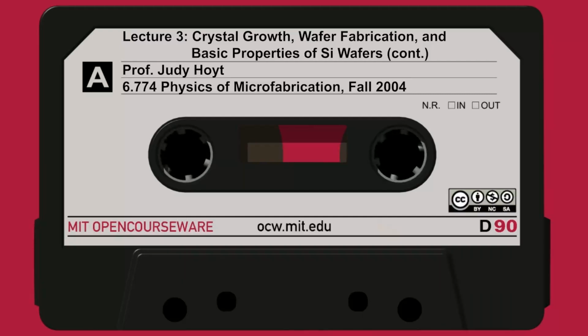Below it is the wafer. And this is the top row of surface atoms. I can take an atom off the surface, and it's not 4-fold bonded, because by nature, the surface is a point of discontinuity. There are only a couple of bonds for an atom at the surface. It doesn't take much energy to pull that out and put it in the bulk, and create a silicon interstitial. So there are a lot of different ways.